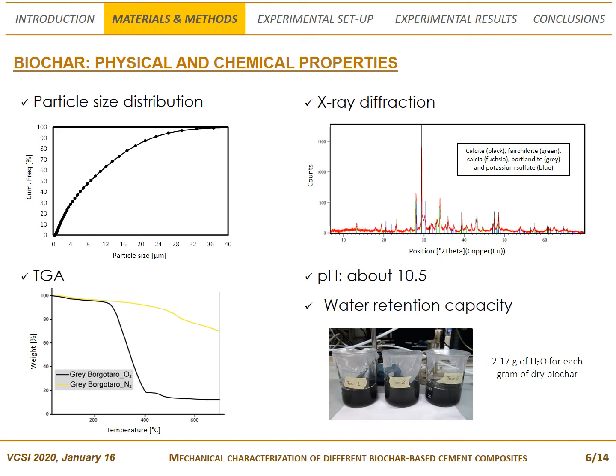As regards pH, tested biochar samples were alkaline, probably due to the presence of organic functional groups, carbonates or organic alkalis. The water retention capacity of biochar, expressed as the mass of the absorbed water per gram of dry biochar, was evaluated by performing a proper water absorption test, which confirmed the capability of biochar to retain water, thanks to the presence of a high number of closely spaced pores able to rapidly absorb moisture.